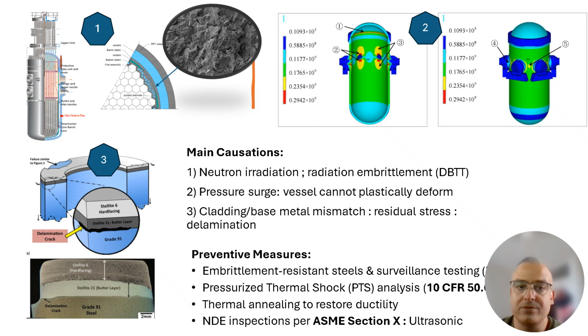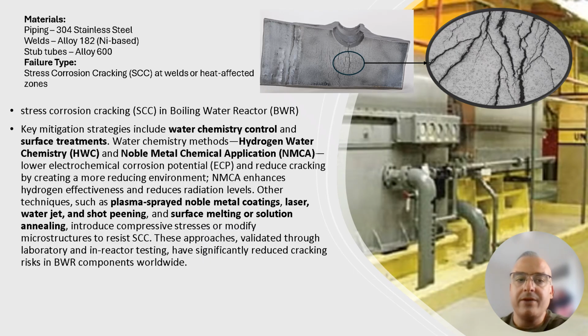The second high-risk spot is the recirculation piping system, especially at the welds where stainless steel pipes are joined to nickel-based alloys. The metals used here, 304 stainless steel and nickel alloys, react differently to the hot reactor water and the stresses from temperature changes. The most common problem is called intergranular stress corrosion cracking, IGSCC, where tiny cracks form along the grain boundaries of the stainless steel under stress.